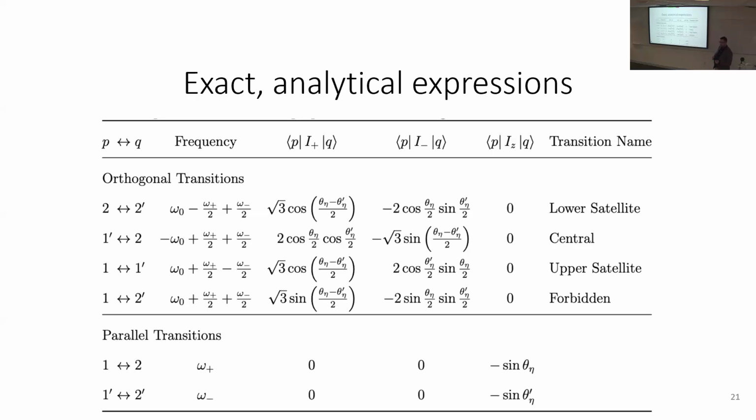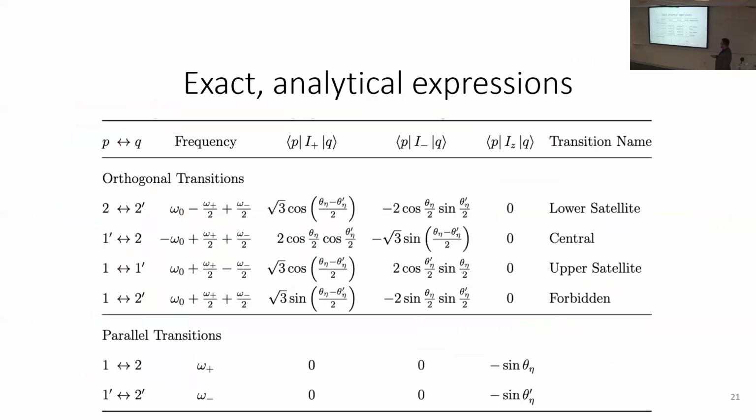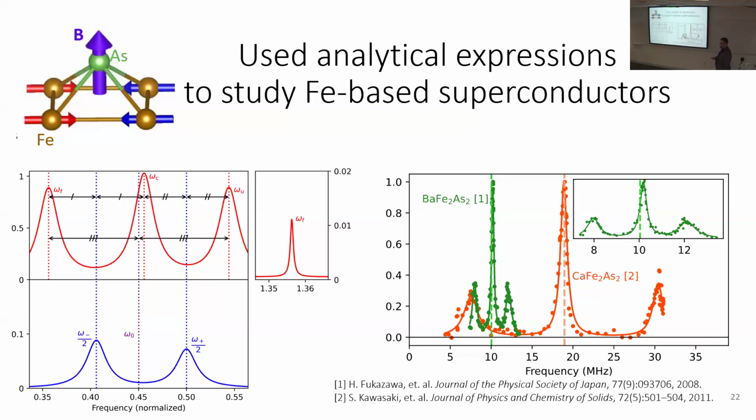An NMR experiment. If I want to measure EFG from the signal that I got from the experiment, what's the process? Well, again, these are the transition frequencies. I would set the appropriate ones equal to these fitted transition frequencies, these three peaks here. So you have to do the peak fitting. I have to do peak fitting first, extract those transition frequencies and set them equal to the right equations that I derived, omega 0, omega plus, and omega minus in terms of the fundamental things.